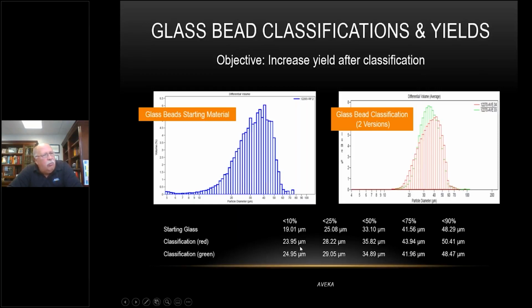If we go to a broad classification, and broad is really not that broad, we're going from 24 microns to 50 microns, about the same D50 particle size. And if we go to a tighter distribution, 25 microns to 48. So that's a 3 micron difference in the distribution of this product. We're cutting right in the middle of this thing, cutting this end off here, and all we're doing is cutting just a little bit tighter in one versus the other. My first look when we set out to do this was that we're really not going to see that much of a change in the yield. But let's take a look at the next slide and see what actually happens.